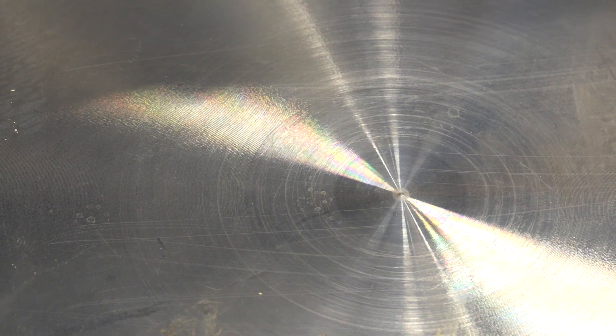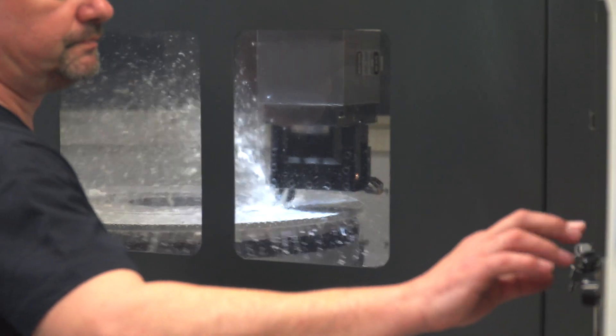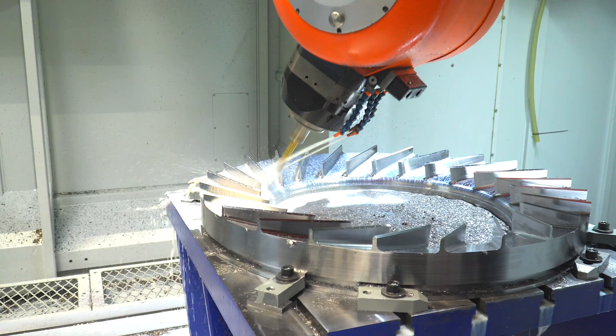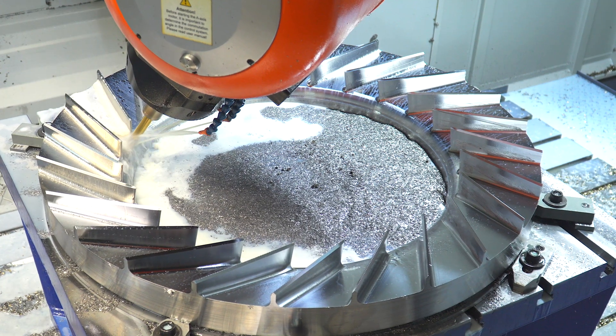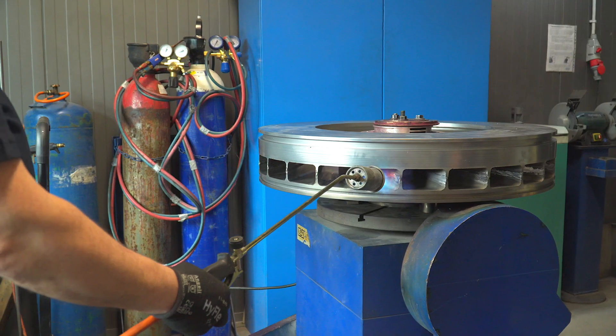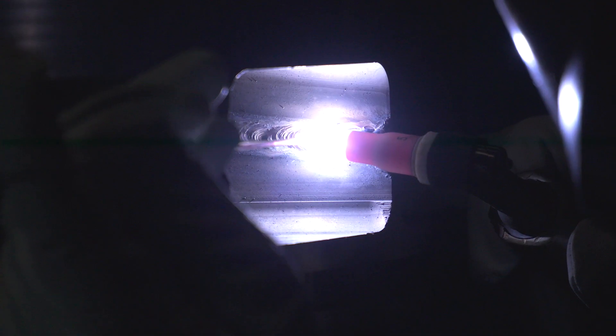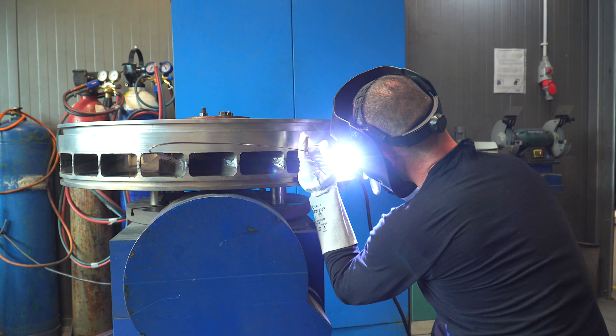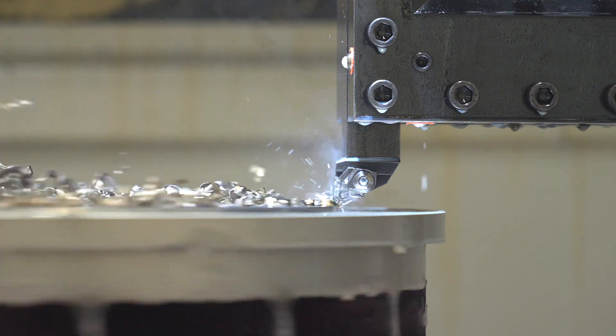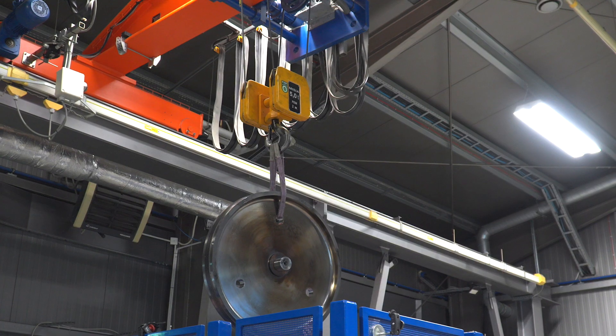Impellers are manufactured from steel, from forged discs of required diameter and height. They are shaped on the lathe, and then transferred onto a 5- or 3-axis milling machine. Some of their diameters are up to 2 meters. Here, the impeller disc and cover are manufactured. Once all blades are milled, fitting and welding begins. If the relevant production technology includes brazing, it is performed in a special vacuum furnace at a temperature exceeding 1,050 degrees Celsius. Then the impellers undergo thermal processing — so-called tempering. After the cover is joined with the disc and machining of blades, the impellers are transferred back to the lathe to obtain the final dimensions specified in the documentation.